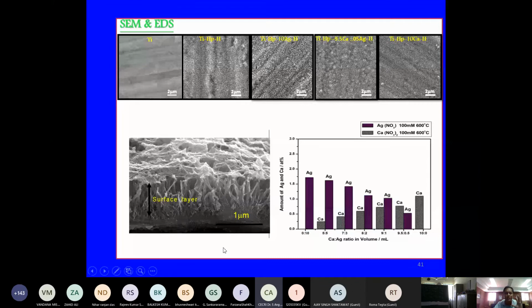This is a cross-sectional image, where you can see how the porous network structure of 1 micron has grown because of the chemical treatment. The idea is that because of the porous network structure, the bone cell can grow through it, and the implant fixation will also be very tight.